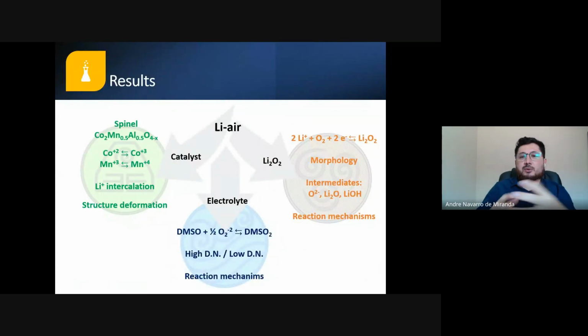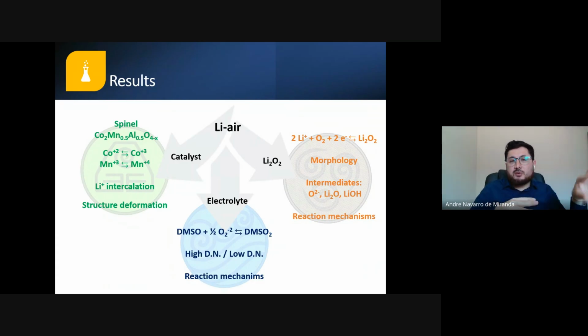So another area that you can study in lithium-air batteries is the catalyst. This is my field of research. In this case, I study this spinel that's made of cobalt, manganese, and aluminum. This material was chosen from different kinds of materials, and it showed really high activity. Cobalt is a nice transition metal oxide to work with. It has different oxidation states: cobalt +2, +3, cobalt 0. We also have manganese, which also has different oxidation states, and it's very active to decompose lithium peroxide.